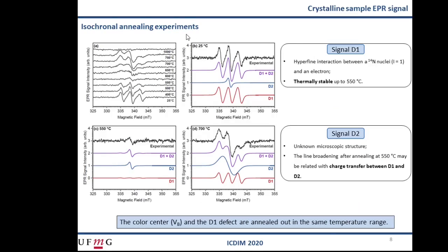For annealing experiments, we heated the samples and after that measured their EPR spectrum. During the thermoannealing experiments, the three hyperfine lines here, labeled as D1, persist until approximately 550 degrees Celsius, and at this temperature, a second EPR signal can be clearly observed, and it is this single line here. This new signal will be labeled as D2. At this point, the sample also loses its pink color, which is the optical signature that the boron vacancy, the spin-worn center, was also annealed out.